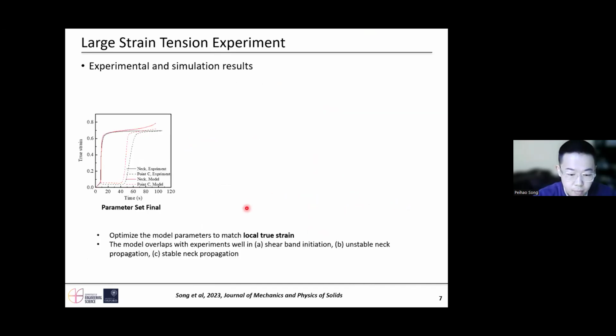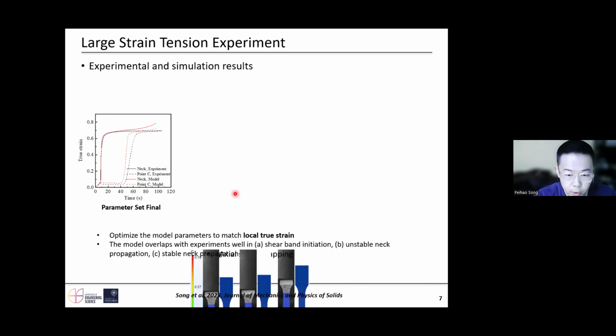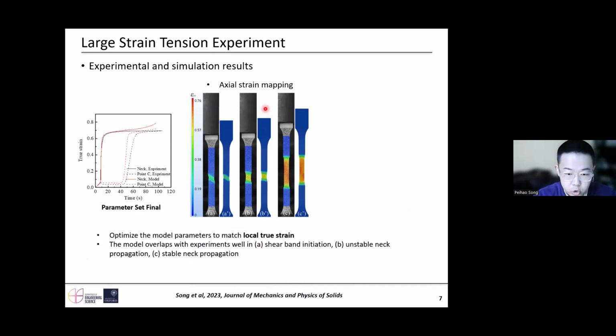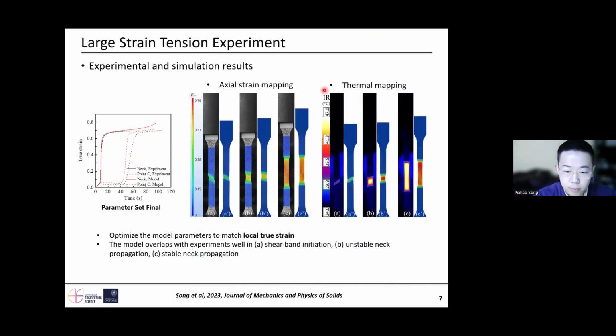So I optimize the model parameters to match the local behavior, and the model here can simulate the axial strain quite well and can simulate the thermal mapping quite well in shear band formation, unstable neck propagation, and to the stable neck propagation to the end of this test.